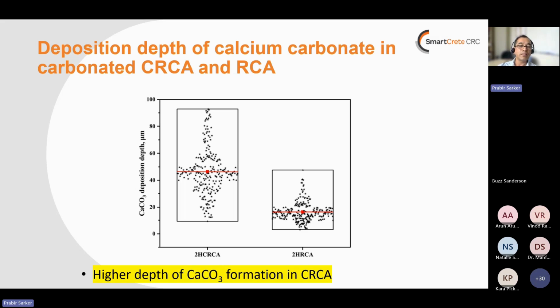So we can see there is more carbonation happening in the CRCA. The reason could be that this concrete was just dumped without proper compaction and curing, so there were more unreacted calcium cement particles available, which could contribute to calcium hydroxide and formation of calcite. So there was more pore filling effect of the carbonation in the CRCA as compared to the other recycled aggregate.